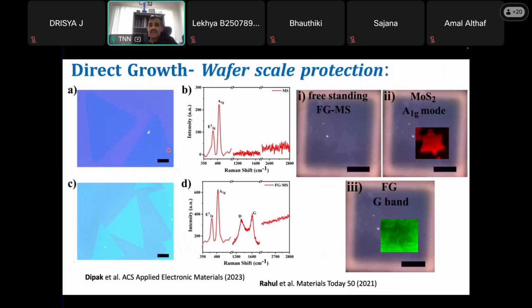Now, what we showed is that we can address this issue by some other kind of carbon deposition. So we could do an in situ carbon, a kind of amorphous carbon layer. We call it the fluorographene layer. It's a disordered carbon, an ultrathin disordered carbon. It has very interesting properties like very nice ion transport, etc. But I'm not going into that. Just after the growth, this membrane can be grown on wafer scale on top of the MoS2 itself. As I said, the MoS2 gets protected here. So this can be done immediately after the MoS2 growth without even exposing the MoS2 to the environment.